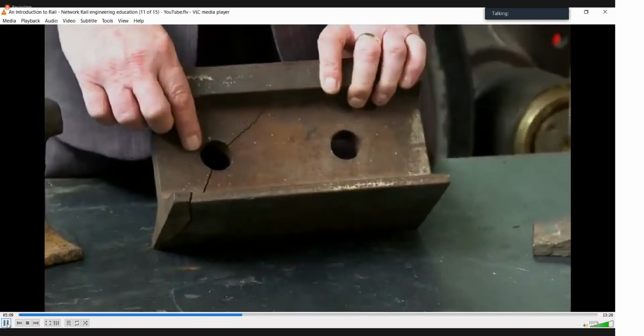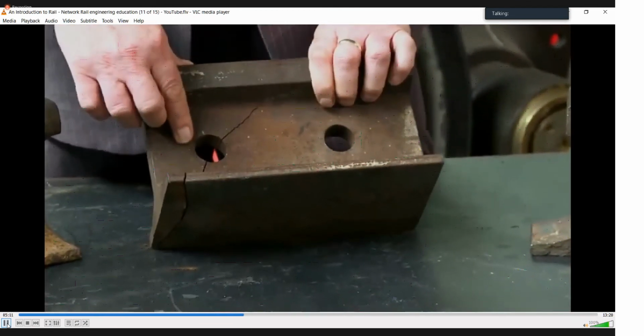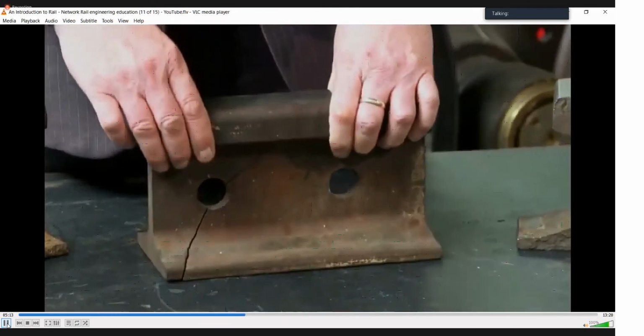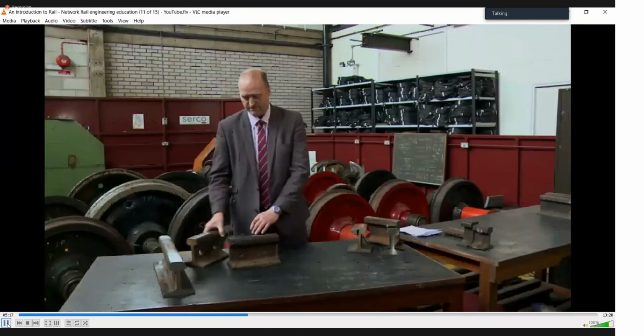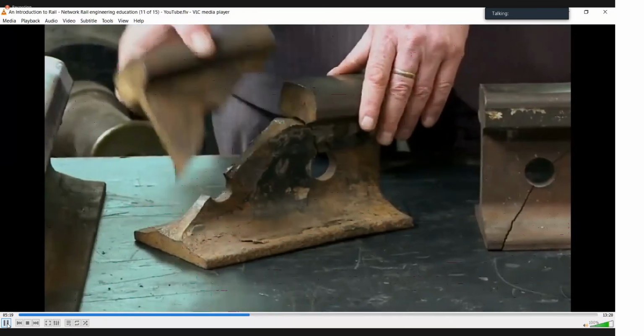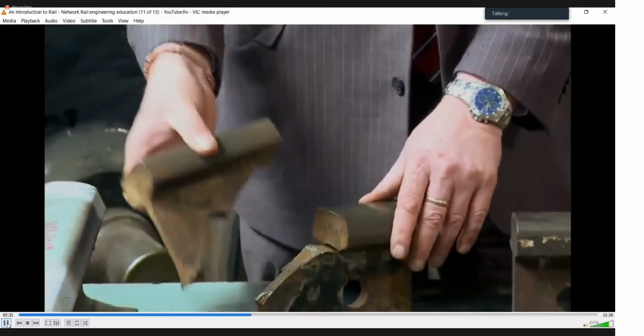Other forms of fatigue that we see, here we have a large star crack which is originated from the bolt hole at a rail end. Equally, these are defects we need to manage. If they're allowed to go to failure, can result in a piece of the railhead becoming detached.